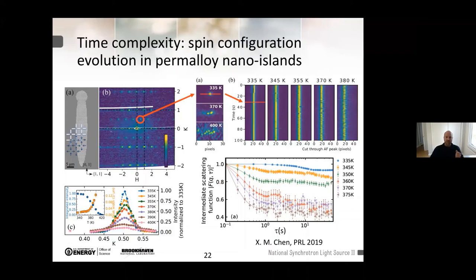And you see that once again you have an evolution of the average parameters versus temperature that is the expected one, right? You have a second-order phase transition, fluctuations or better correlations go up, so width and maximum, peak width, call it as you want, go up. And everything works exactly as we saw in the cuprates, but we discovered that there was much more underneath. And here we have the impression that it's the same as well. Because if you fit the intermediate scattering function versus time, the initial part can give you the activation energy, essentially what you're looking at, which is a collective motion, domain motion, of the magnetic ordering in your sample.